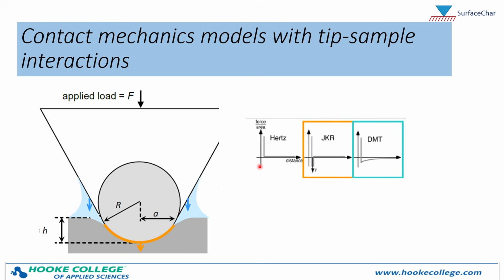The practical significance between these two models is that depending on your sample, sometimes you might want to use it, or you might need the JKR model instead of the DMT model, and vice versa. So many samples that have only a little bit of adhesion that you might image in AFM, the DMT model might be sufficient. But for those stickier samples, ones that I tend to work with a lot are rubbers or elastomers. They certainly require a model like the JKR model.